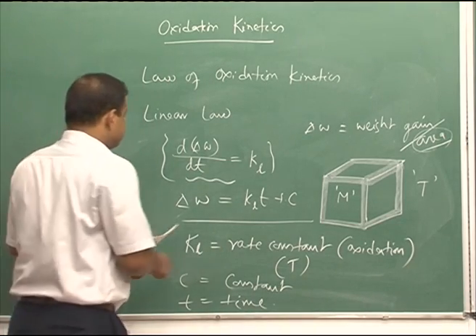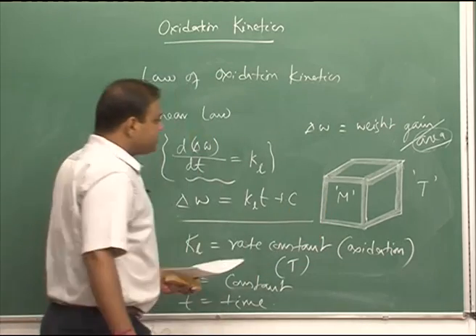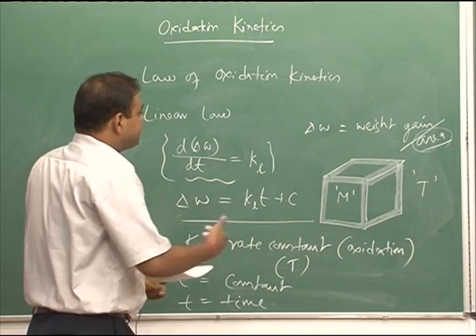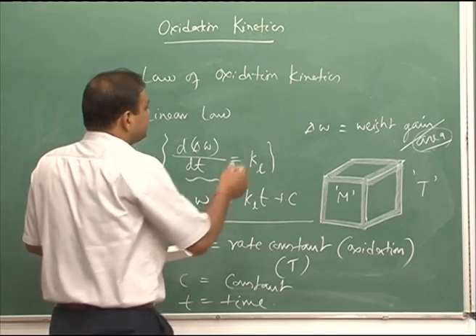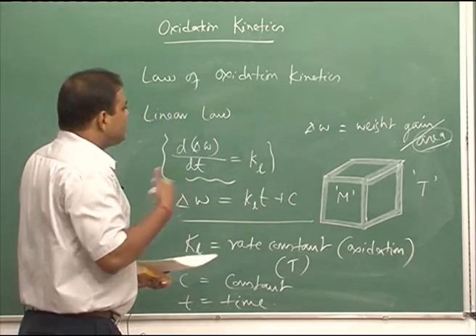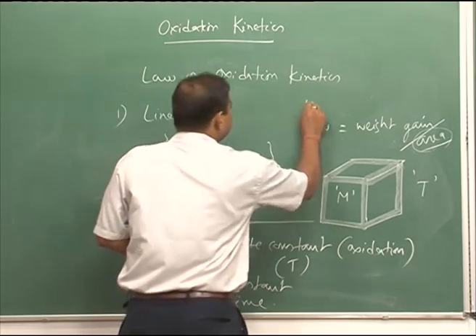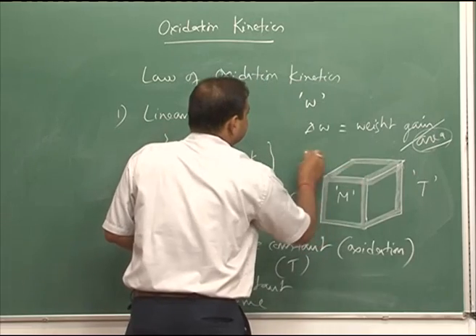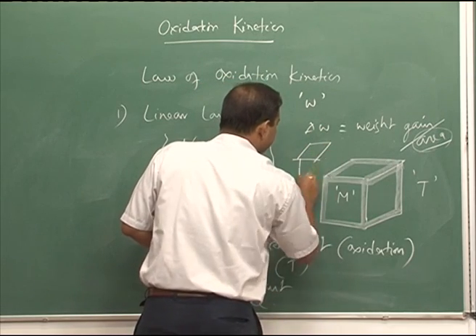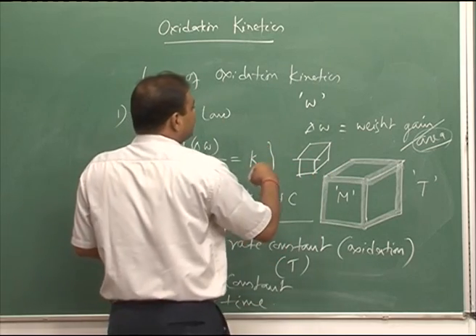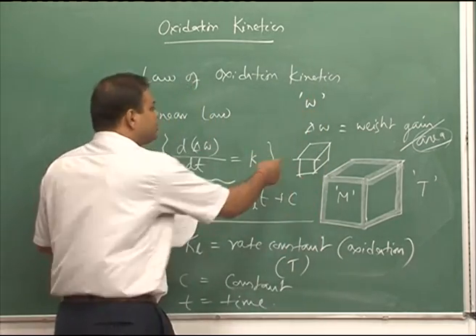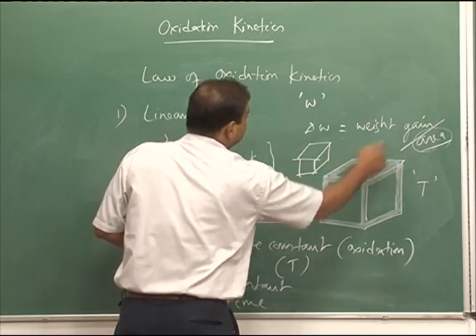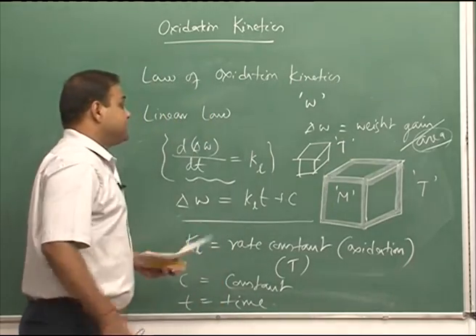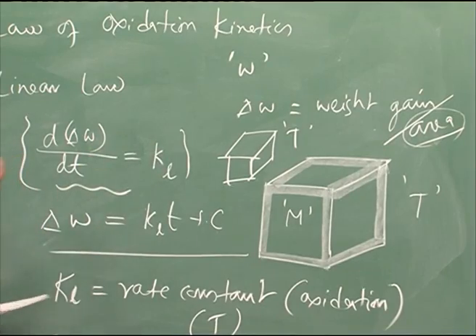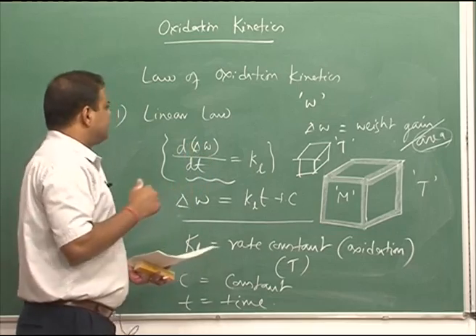Now, we also see that this del W is nothing but the weight gain per unit area, in order to depict the oxidation process properly, since if we consider only the weight, then it will not give you the actual picture, because if we consider a larger area or a smaller area, the weight gain would be different. But the weight gain per unit area, if this is taking place at temperature T, would be the same if this is following the linear law at that particular temperature. And the same thing happens in the case of other laws.